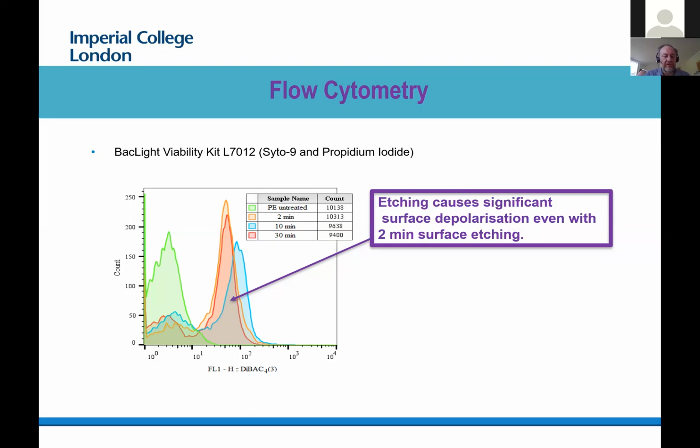So what you can see simply here is as we go from the PE, where the cells are all on the left and are viable cells, the cells that are in contact with the polyethylene that has been treated, those cells are much less viable. So which sort of confirms independently that the oxidized polymers affect the viability of the cells. So the cells are being compromised by the surface chemistry of the polymers.